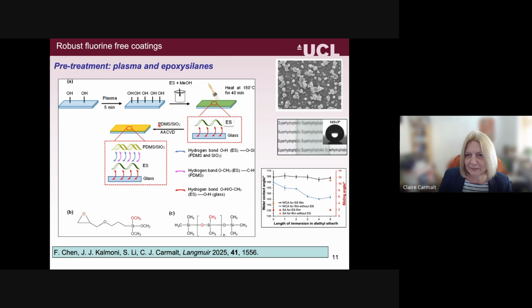This time we just used polydimethylsiloxane with our silica nanoparticles. So we got no fluorine present there, and that deposited on the top layer. You can see the SEM over here, and they were really good films in terms of their adherence. They're not quite as transparent as we'd like, but the transparency is not too bad. So I think we can improve this, and they have a very high water contact angle.